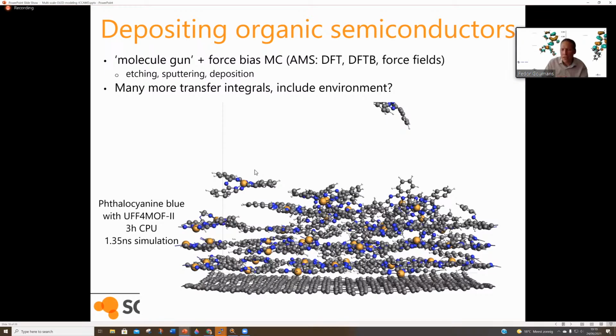And there are a number of physical processes that they put in their kinetic Monte Carlo method for their device modeling. And so all the relevant electronic processes are there, all the relevant excitonic processes are there, as well as the degradation processes. Of course, this kinetic Monte Carlo, it just needs rates. It's very agnostic as to where it gets the rates from. So it can be experimental, it can be computed rates, it can be a combination of both, and eventually it can even be machine learned rates that use a combination of both experimental and computed data.